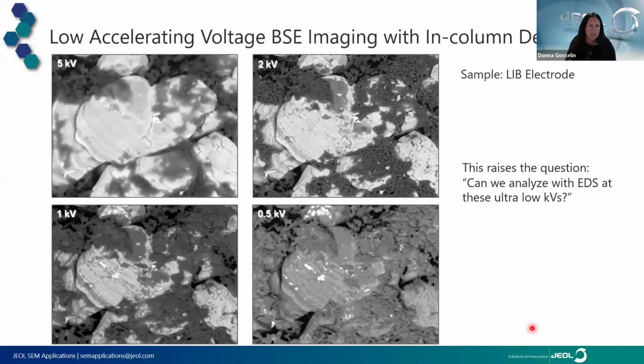So next I want to discuss some low voltage analysis, to keep within that theme. What we're seeing here is an electrode image that was collected at 4 different voltages: 5 kV, 2 kV, 1 kV, and 500 volts. And if we focus just on the 2 kV and 1 kV images, you can clearly see that there are 2 different types of grayscale compositions, even texture here, a darker gray and a lighter gray that's sitting on these particles.